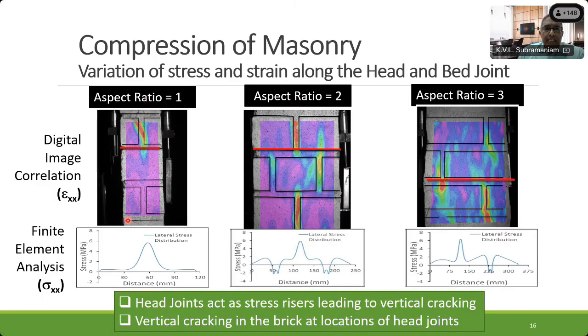Now, this is one particular arrangement of bricks where we have a head joint and a bed joint. Then there is masonry, another bed joint and head joint, and so on. And that pattern repeats itself. The aspect ratio is 1. That means if you look at the cross section of the specimen, it is 1:1. What we find is that in this particular masonry specimen, there is a lot of tension that is produced even in the head joint here. And that tension that you can see here, we plotted the strain along here, and from there we simply calculated the stress. We find that very heavy tension is produced in the mortar, which we expect.